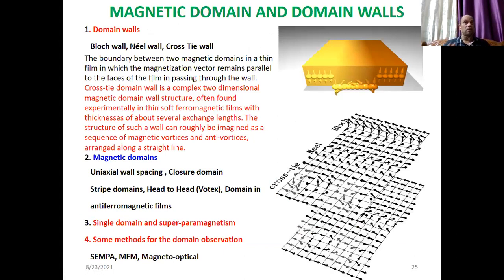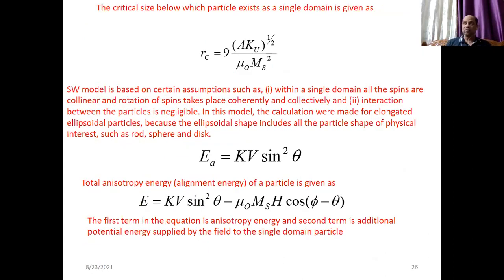I will tell you that the magnetic properties of the material can be tuned by doing this grain boundary engineering in thin film. Very interesting applications have come. People have developed different kinds of memory devices by changing the perpendicular magnetism and the parallel magnetism. So memory devices and spintronics are also developed. The critical diameter that I told you should be less than 100 nanometer. This is the example of a simple cubic; if anybody is interested, they can go inside and find out different structures.